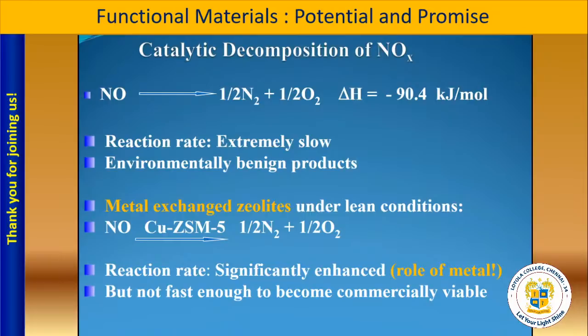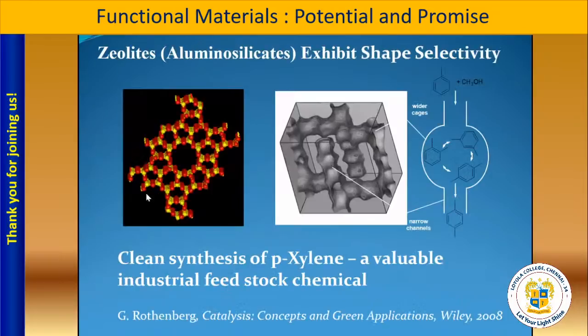that catalyzes this reaction. So this is a typical zeolite, ZSM5, which has three-dimensional channels and pores. Now, there is not much time to go into details, but suffice to say that they have well-defined channels. Because of this, they exhibit what is known as shape selectivity. So here is an example that out of three products which could be formed in this reaction, it selectively generates only the rod-shaped molecules because of the strict size.